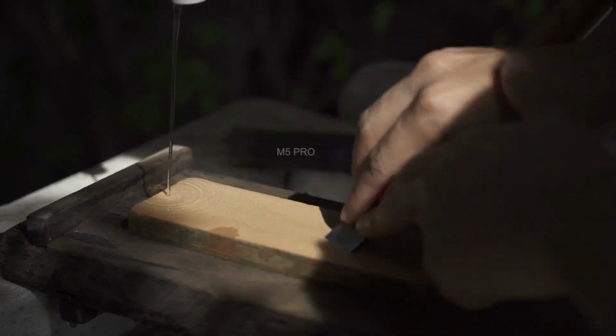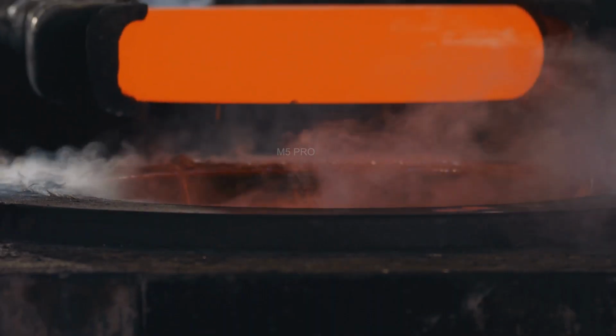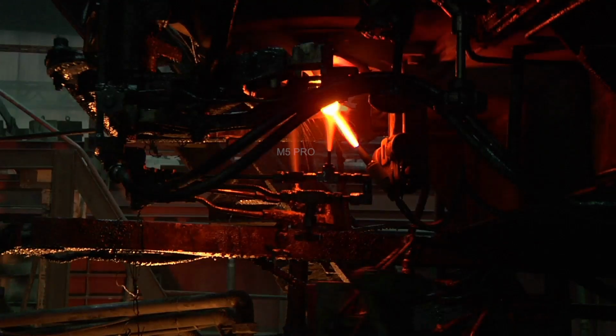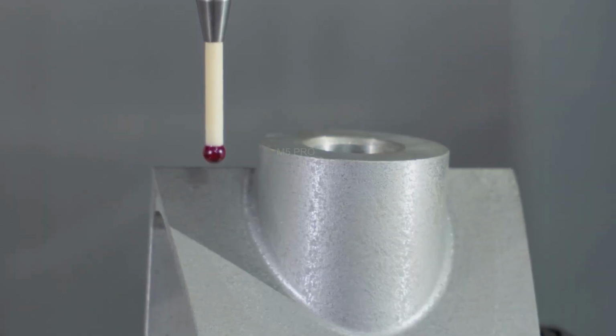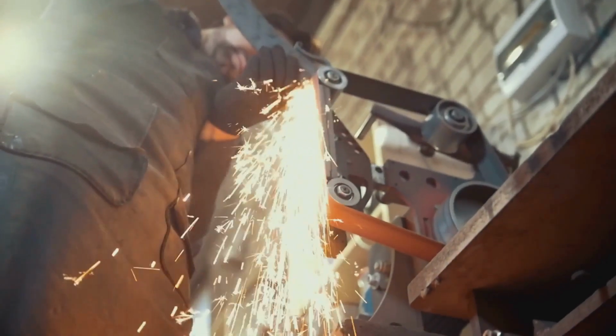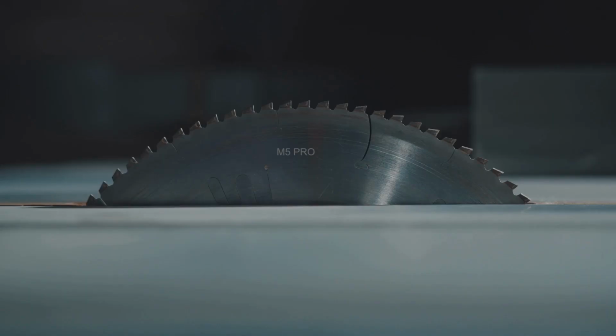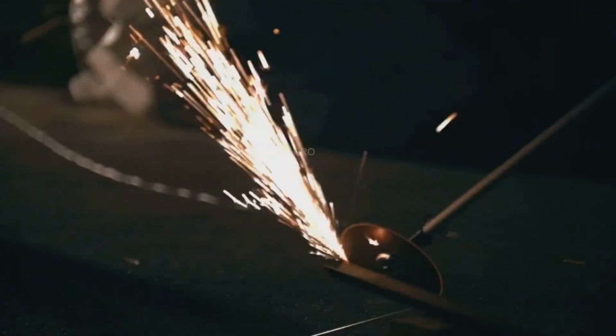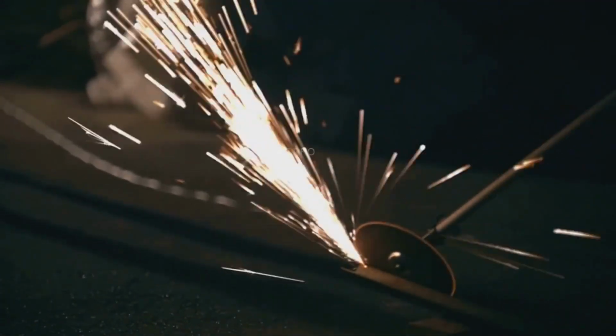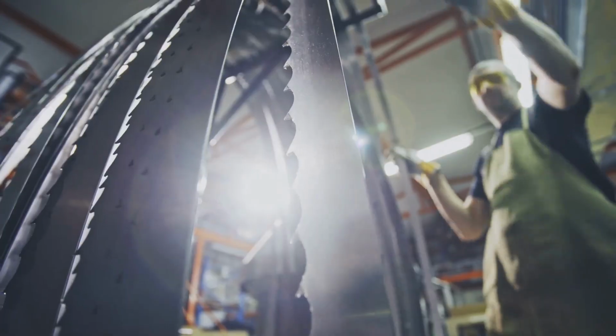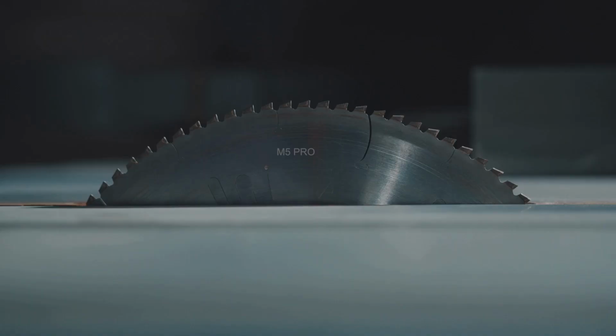Our cleaver has come a long way. It has survived the fire of the forge, the shock of the quench, and the tempering heat. It's tough and hard. The rough grind has given it its basic shape, but it's still crude. The surface is coarse from the aggressive grinding belts. Now it's time for the finishing touches. We take the blade from a roughly shaped tool to a refined instrument.